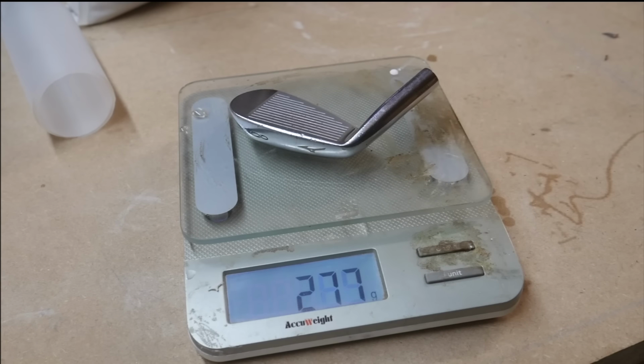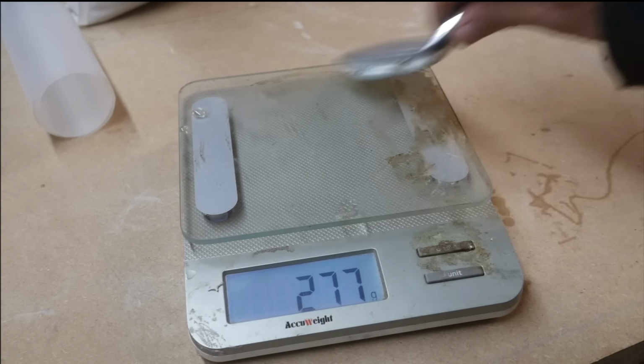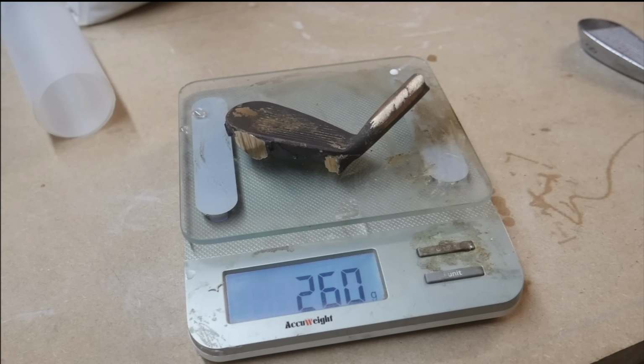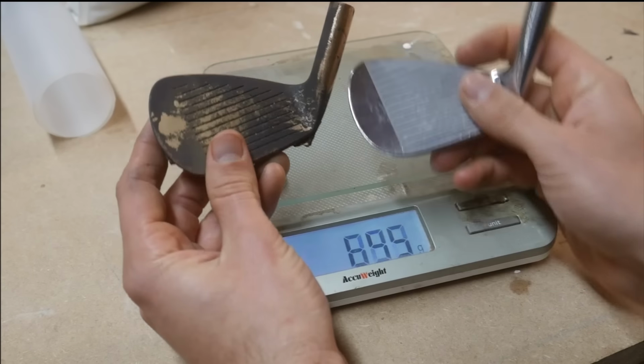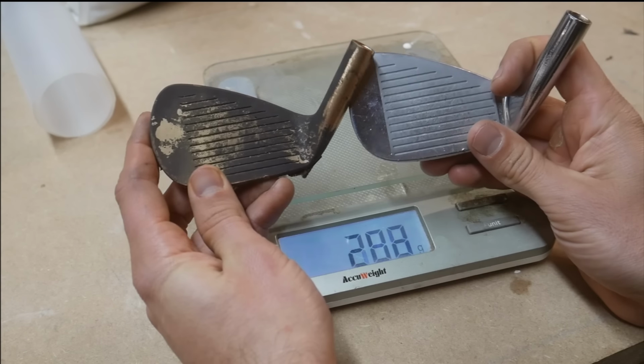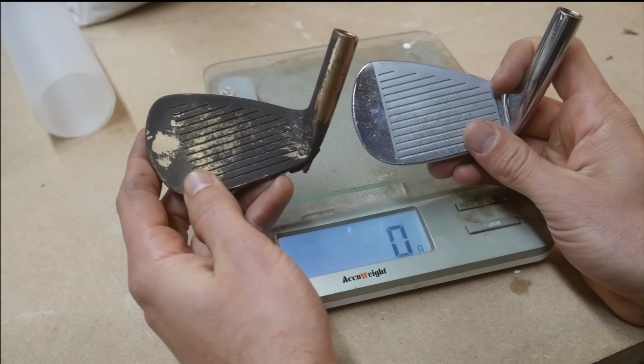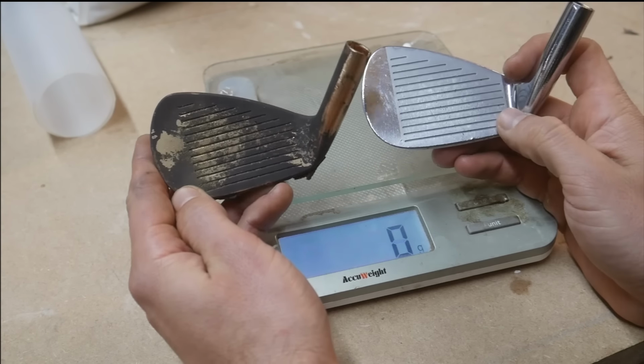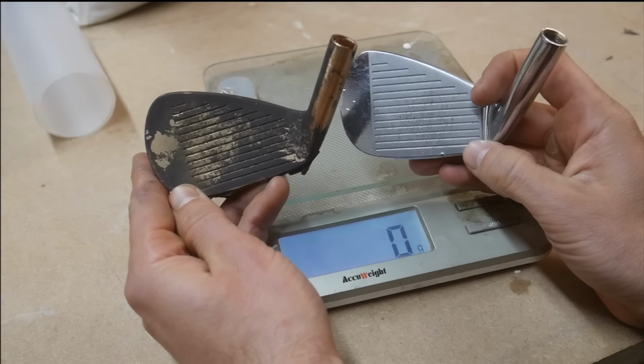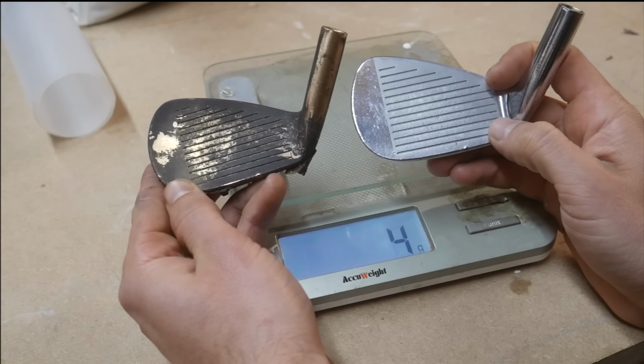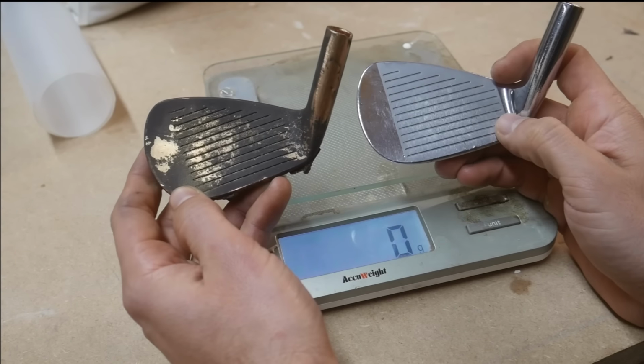8 iron, 277 grams for the Mizuno, 260 for the bronze, and I still gotta clean this one up too. That's a big discrepancy, so I'm thinking some of the weight difference is due to metal shrinkage while cooling. I'm not sure if you can visually see it, but the hosel on the bronze iron is slightly thinner, so I think metal shrinkage is at least a small factor too.